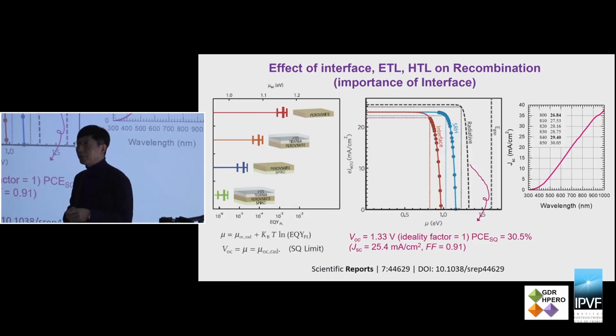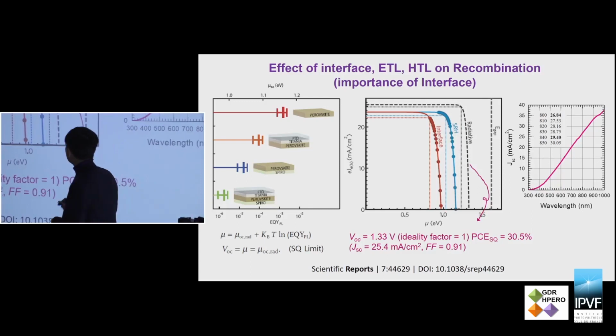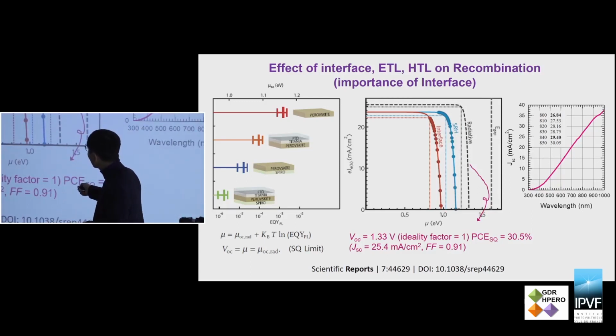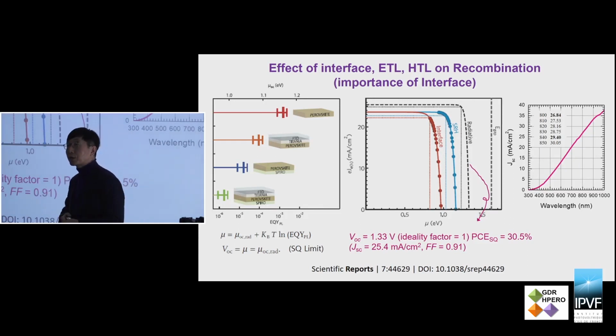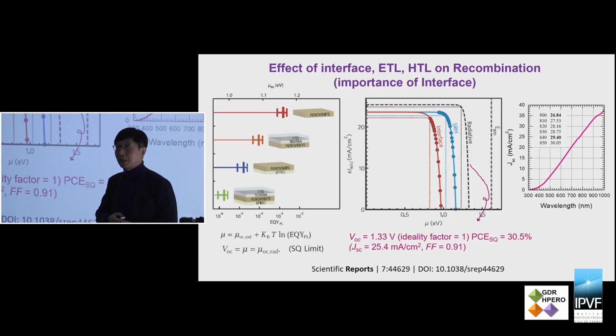If you increase defects inside the perovskite material, that is called SRH recombination. Then you further decrease the short circuit photocurrent density, slightly the fill factor, and also lose a large amount of open circuit voltage, to about 1.17 or something like that. If you further introduce interfacial recombination because of the ETL and HTL layers, the open circuit voltage decreases further without any change in short circuit photocurrent density. If you are working on perovskite solar cells, you can find this phenomenon frequently. This is due to interfacial engineering. So why do some people get 25% efficiency? Probably they can control the SRH recombination and interfacial recombination very well.